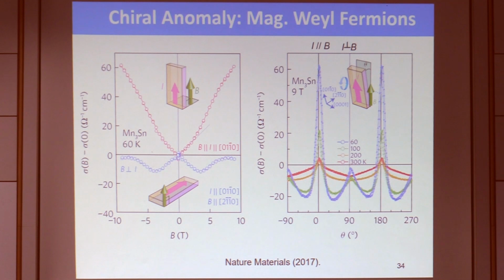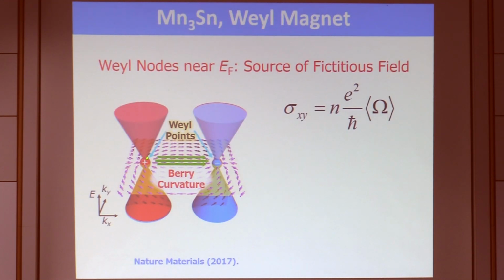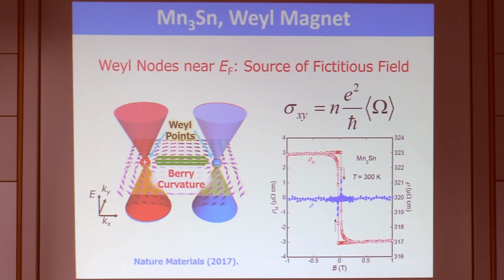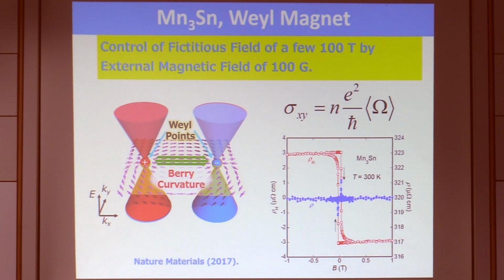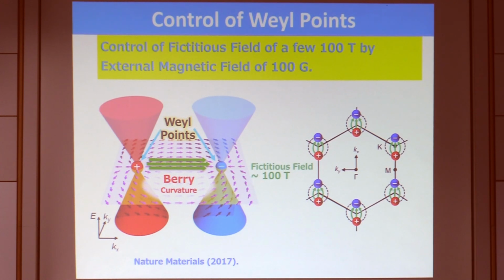So these indicate that these Weyl nodes are indeed located near the Fermi energy and partially contribute to the whole conductivity. Another interesting point is that one can change its sign by a few hundred Gauss, indicating that one can control the large Berry curvature in this material, of the order of a few hundred Tesla, by just a few hundred Gauss. So obviously what we have to do as a next step is to use electrical means to control the configuration of the magnetic Weyl points in momentum space.